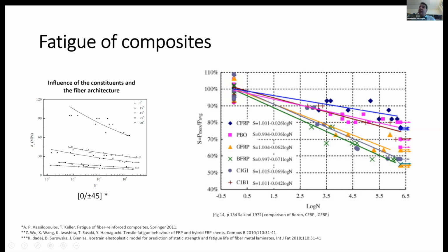What is important here to show is that, first of all, the materials that are better in performance, like carbon, show also a very, very low slope in the S-N curve. The materials that are not so good show bigger slopes on the S-N curve, which means that if we test at high stress levels or low stress levels, we can increase the life by far in the good materials, not so much in the less performant materials.